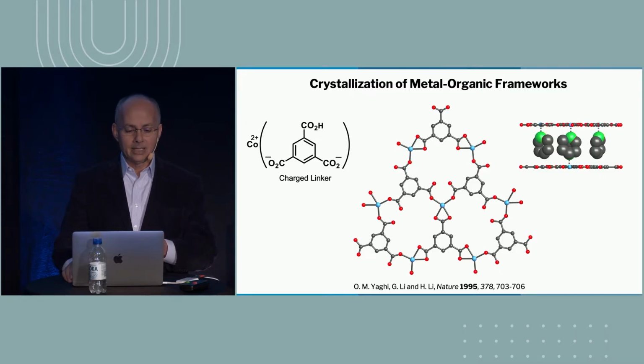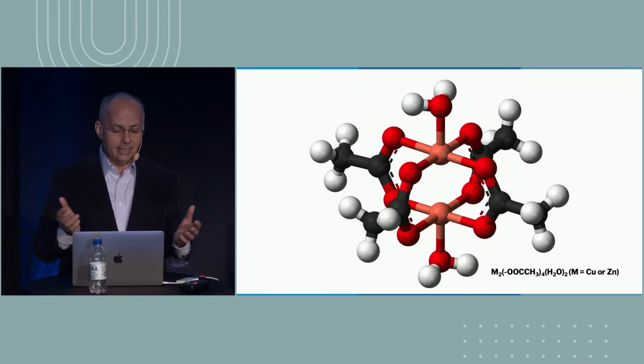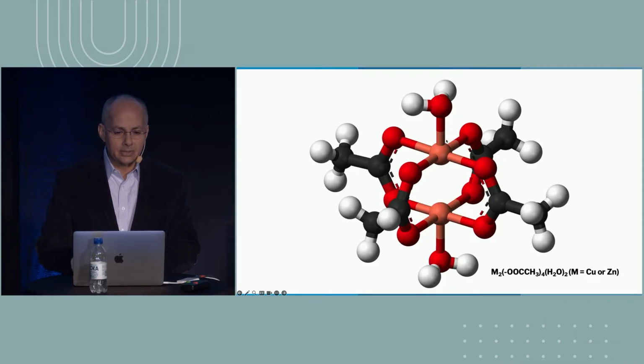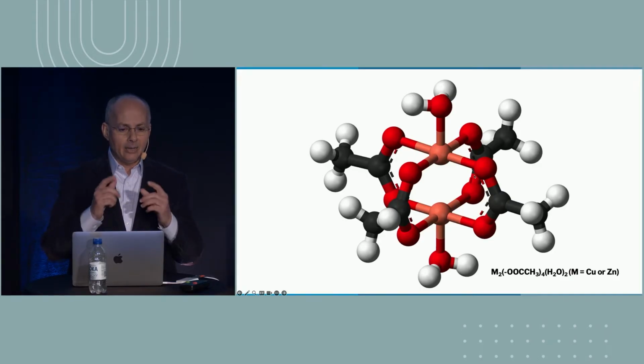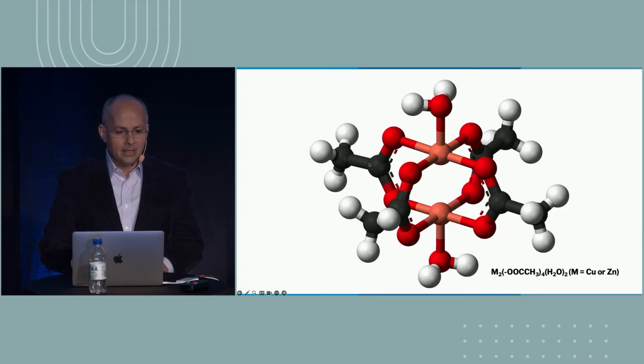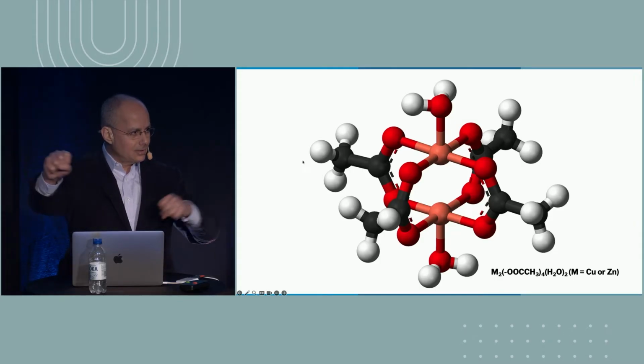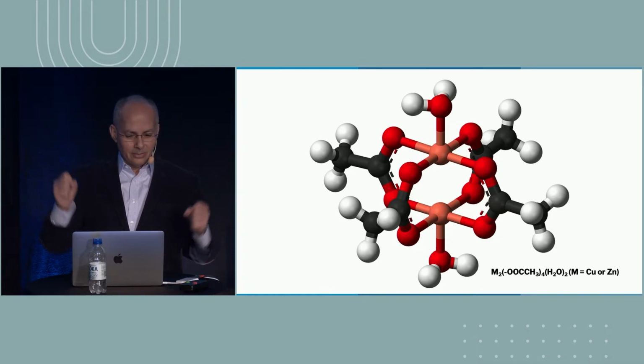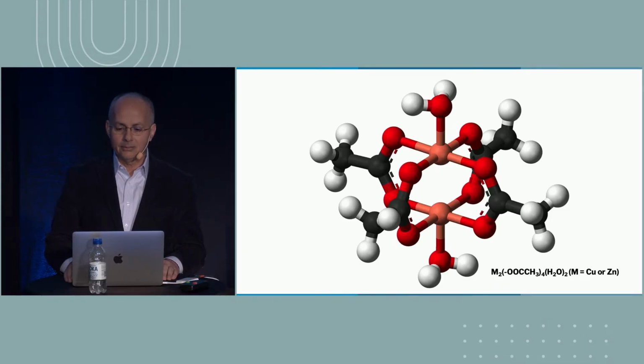further, and we wanted to understand the conditions under which these compounds crystallize. So we looked in the literature, and every inorganic chemist, every chemist should know that the metal acetates, the copper acetates and zinc acetates have this structure. They're molecules, and the core of these molecules is basically a dimer of metal, either copper or zinc, that is bridged, and you learned about chelation, I'm sure, bridged by a carboxylate. So by 4 carboxylates, you can see that it's bridged by 4 carboxylates. So our idea was that instead of acetate, if I can have a diacetate, then I could extend this structure infinitely. And what could those materials be like, and what properties would they have?